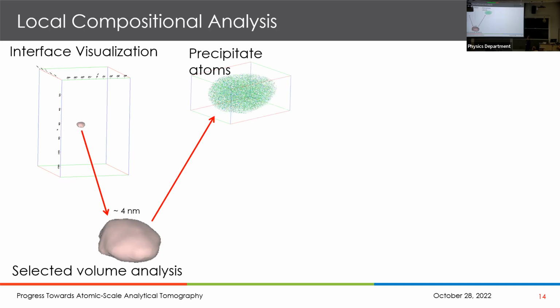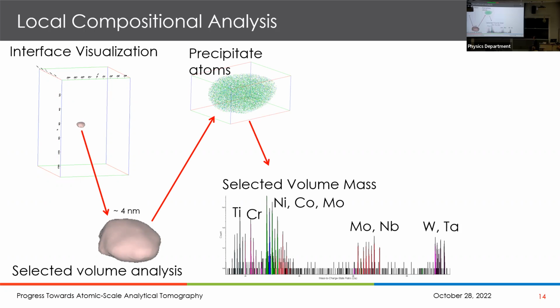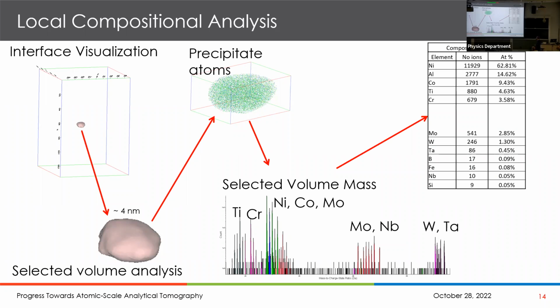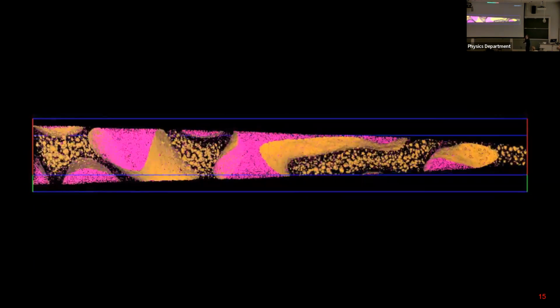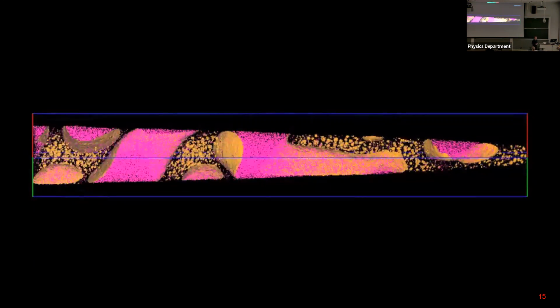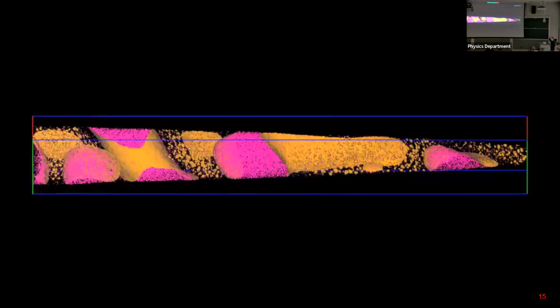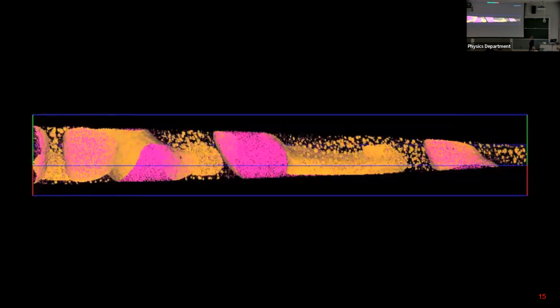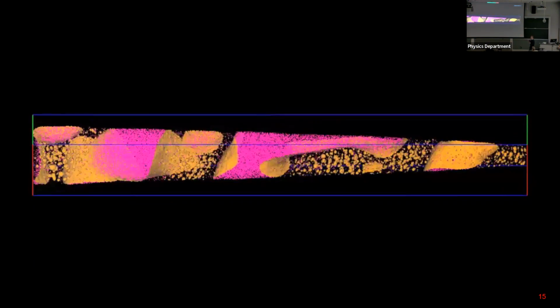But we can go further. Wait, there's more. You can look at just the atoms that are inside that precipitate, and you can actually look at the mass spectrum of that precipitate. You could do that for each and every precipitate or other phase. And in fact, there's the composition of that one precipitate in this case. And as I say, you can do it if you want for every one of the precipitates, and then start interrogating these kinds of images. So there's a rich three-dimensional character to atom probe tomography information. If we could just fix a few things like the spatial fidelity, and ideally this is only 60 or 80% of the atoms. In some cases, we'd like to have every single atom.